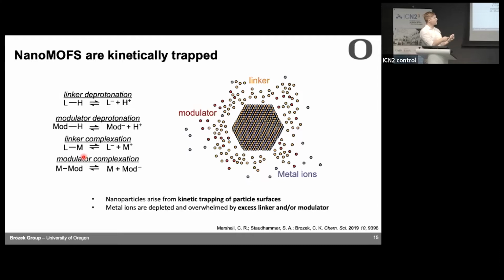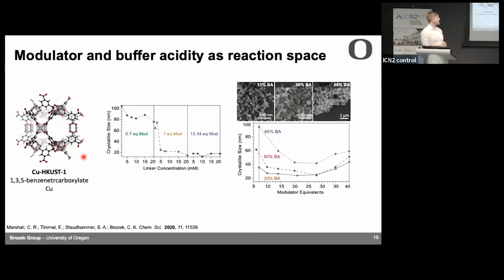And so with this model, we've been able to reproducibly control the size of lots of different MOFs. So for example, we're focusing on this iconic MOF, copper HKUST1, also known as copper BTC, and we could study how different common synthetic parameters impact the size. And so these three panels, for instance, are almost the same experiment, except each panel is using different equivalents of modulator. And then we plot the size as a function of how much linker, the concentration of linker. And we see that as you increase the concentration of linker, you consume more of those metal ions. It does make the sizes smaller, but what seems to matter even more is how much modulator you